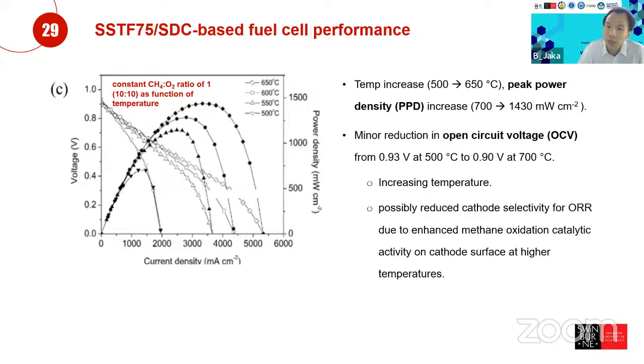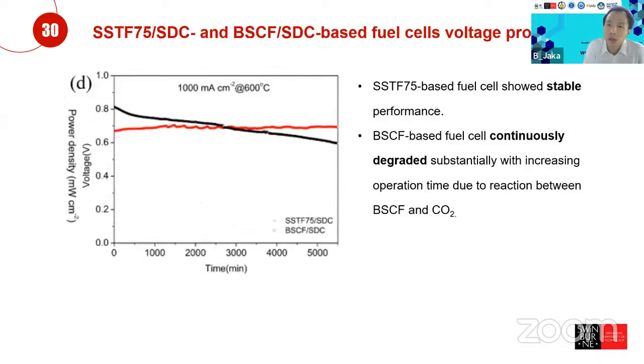Then we pick one ratio of the CH4 with the O2, and we probe it again. We see that there is a bit of reduction in the OCV from 0.93 to 0.9. This is due to the increasing temperature and reduced cathode selectivity for oxygen reduction reaction, due to enhanced methane oxidation catalytic activity on the cathode surface at higher temperatures. This one in here is showing the test as a function of time.